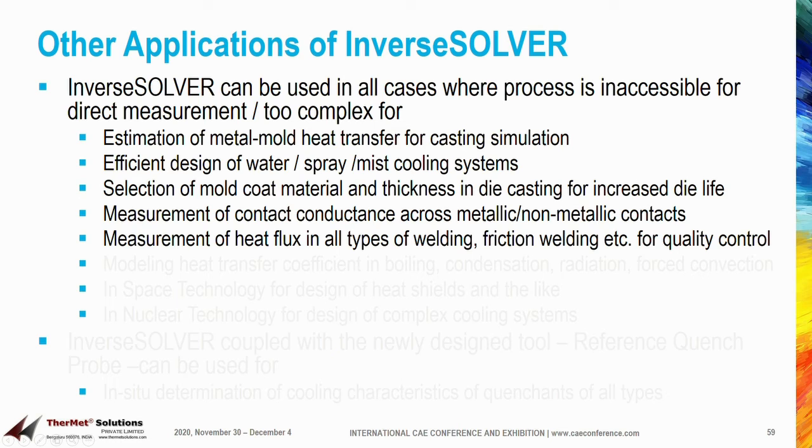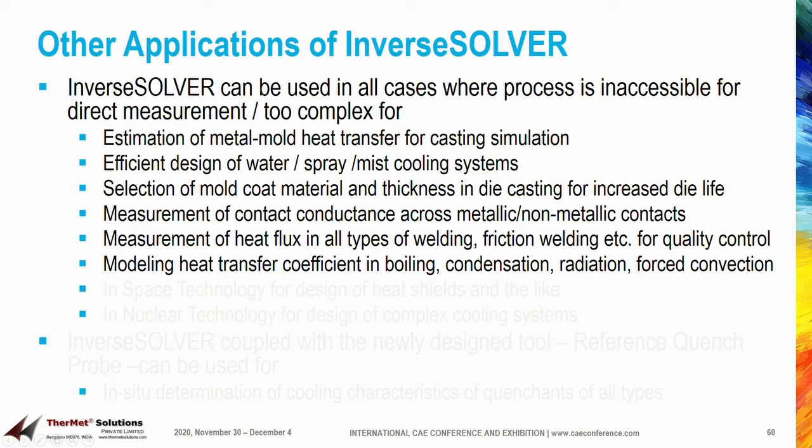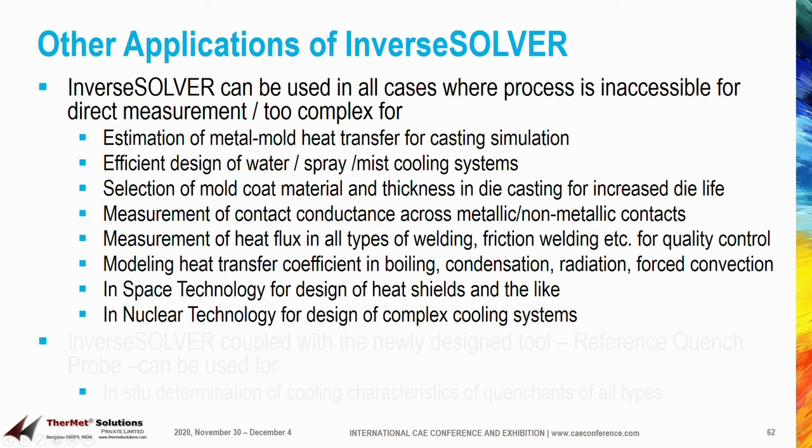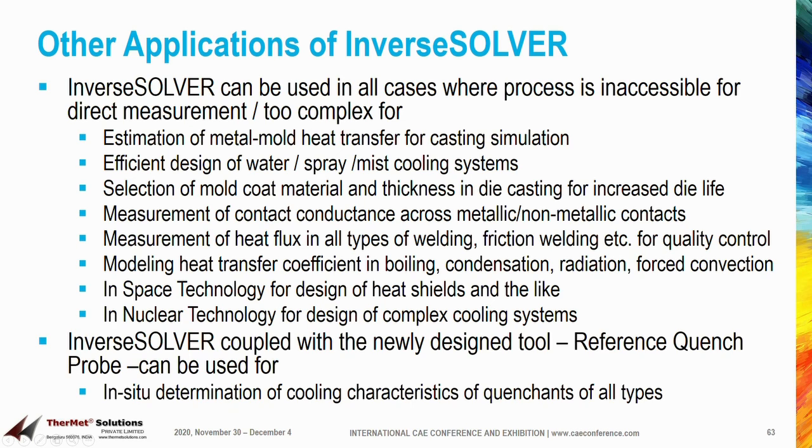For quality control, modeling heat transfer coefficient in boiling, condensation, radiation, forced convection, in space technology for design of heat shields and the like, in nuclear technology for design of complex cooling systems. Inverse solver coupled with the newly designed tool reference quench probe can be used for in situ determination of cooling characteristics of quenchants of all types.